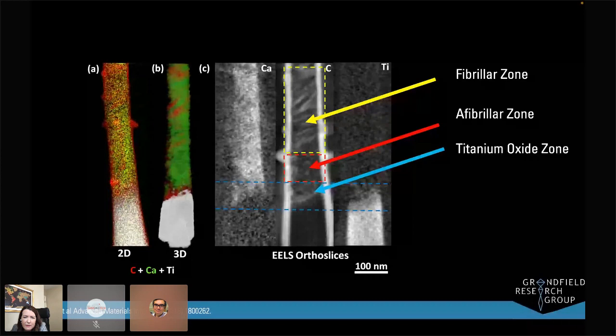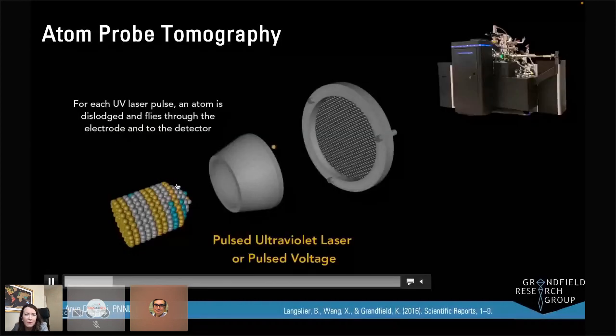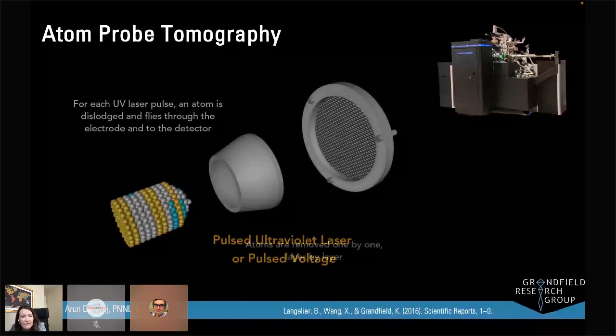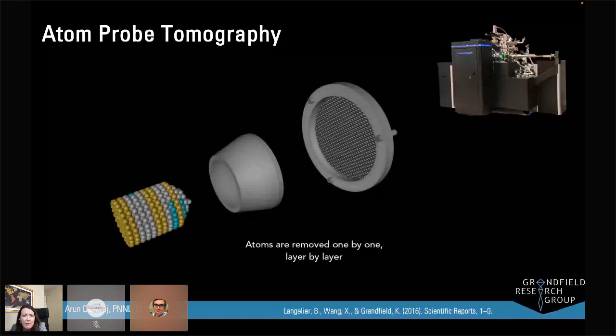We couldn't probe this with EELS. It wasn't high enough resolution, although it's quite high. So what we wanted to do was take this same sample and probe it with another technique called atom probe tomography. An atom probe microscope is a really interesting microscope. You take a cylindrical shaped sample that has a really pointed tip, similar to what we've already used, and by applying a laser pulse to the end of the sample, you can create field evaporation.